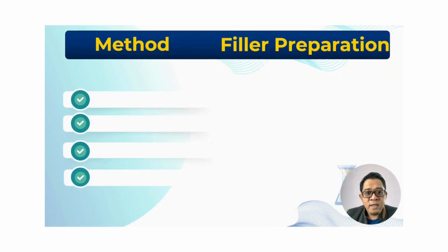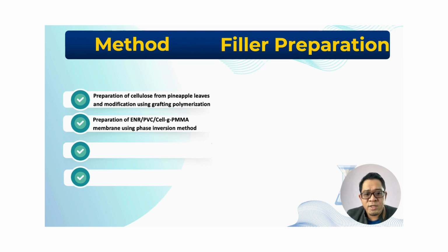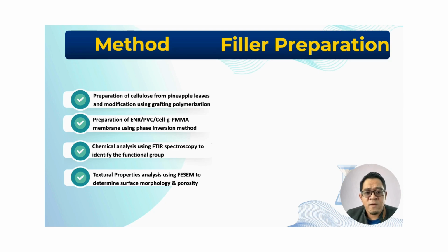For the method, there are several steps to prepare the ENR PVC cellulose grafted PMMA. First, preparation of cellulose from pineapple leaf and modification using grafting polymerization. Next, preparation of the ENR PVC cellulose grafted PMMA membrane using the phase inversion method. And then, chemical analysis using FTIR spectroscopy to identify the functional groups. Next, textural analysis using FESEM to determine surface morphology and porosity.